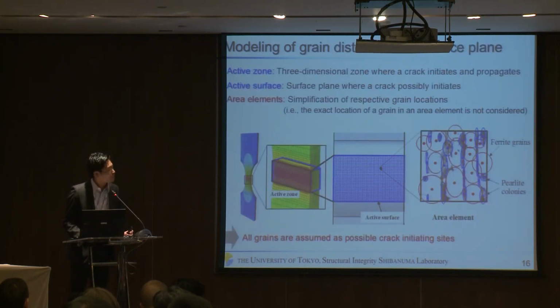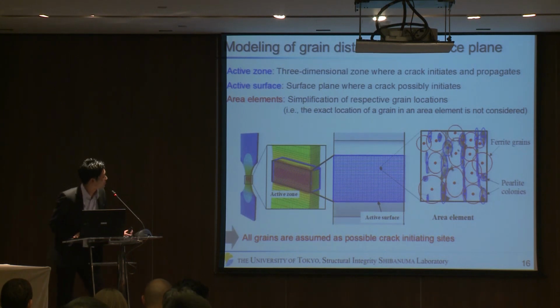Next, okay, so I'll explain the modeling of grain distribution in the surface plane. In FEA, active zone, active surface and area elements are defined. Each grain is randomly defined in an area element, and all grains are assumed to be possible crack initiating sites. So when the loading is over the resistance of the grain, a crack initiates.